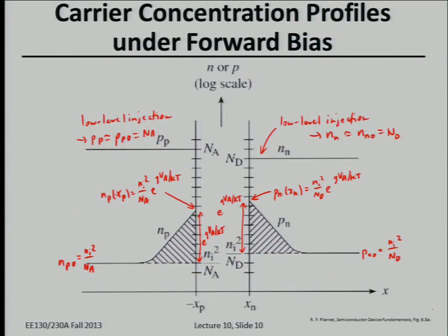Okay, so this is just to remind you, a diode under forward bias, you have excess minority carriers whose concentration decays exponentially. This is a log plot, so it looks like a straight line here. The excess minority carrier concentrations at the edges of the depletion region depend on n_i squared. And the higher the excess minority carrier concentration at the edge of the depletion region, the more concentration gradient you have, because you go from that concentration to 0, essentially, right? Excess carrier concentration to 0 in the quasi-neutral region. So let's say this is the emitter on the left. If the band gap is narrower, then n_i squared will be higher. And so you'll see the excess minority carriers in the emitter on the left go up, and that means there's more electron diffusion current going into the emitter, which is bad for emitter injection efficiency.